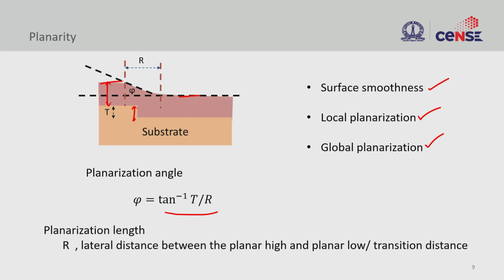But then if you keep on progressing in your polishing process, you will achieve global planarization, and typically your angle is going to be nearly 0. Okay? So once you get 0, that means you have achieved a complete planarity. Okay, so this brings us to the end of understanding the CMP process, right. So what happens on the surface, how the CMP process progresses, starting from a very large topography, very sharp features, and then you try to smoothen it, and then in the next step you get local flatness, and then finally you achieve global flatness.